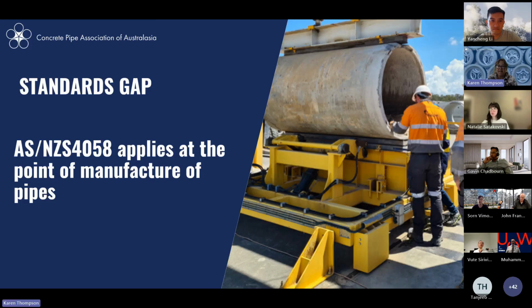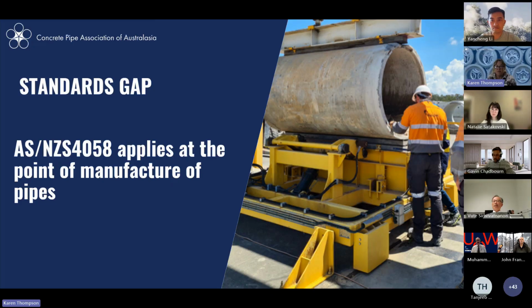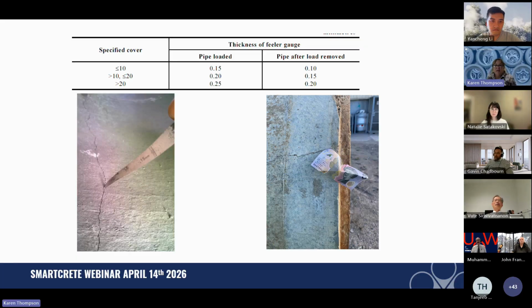We also have a gap in our standards. AS-NZS 4058 is the standard for the manufacture of concrete pipe. It's a performance-based standard. So to verify a pipe as a strength class, the manufacturers perform routine testing of strength on equipment which is shown in the picture. The strength is verified by a given load being applied with a crack of up to a maximum specified value occurring under the load under controlled conditions. The crack width nominated is simply a quality assurance performance indicator. It's not a value that is intended to be the maximum allowable crack width in the field, but it often gets adopted as such. The allowable crack width varies with increasing cover to steel.